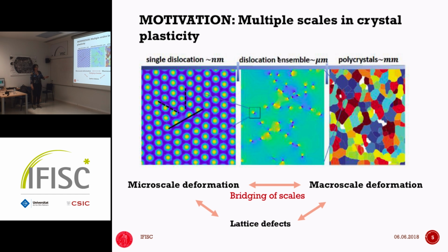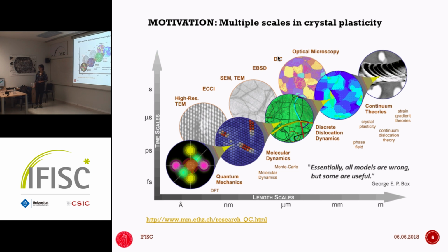You have a bunch of them when you go down to microscale, and when you reach the millimeter scale and larger, you create grain boundaries and polycrystalline structure, and eventually you lose the lattice symmetry, and the material becomes continuous or uniform. So there is this theoretical, fundamental challenge to relate the microscale deformation to the macroscale properties that we're interested in, and how they couple with the lattice defects. This bridging of scales, this interesting multi-scale physics, poses fundamental challenges. And of course, there are many approaches depending on the community.